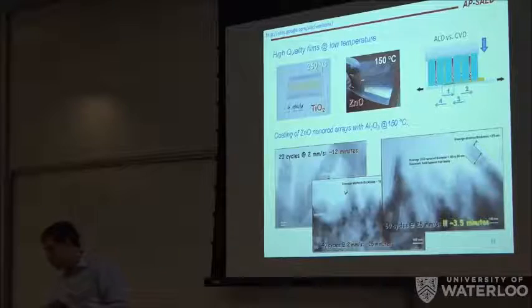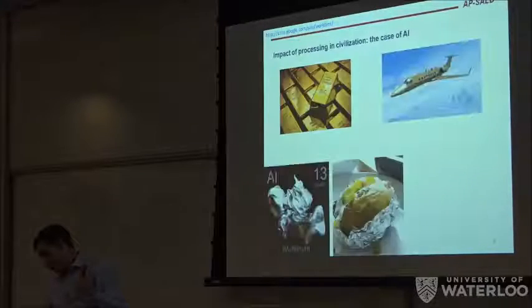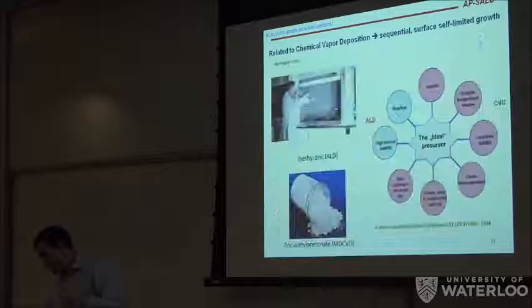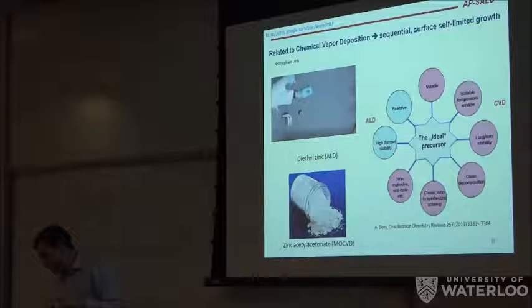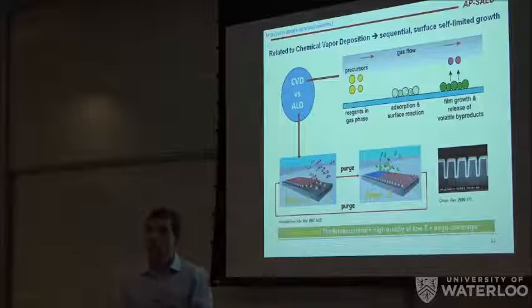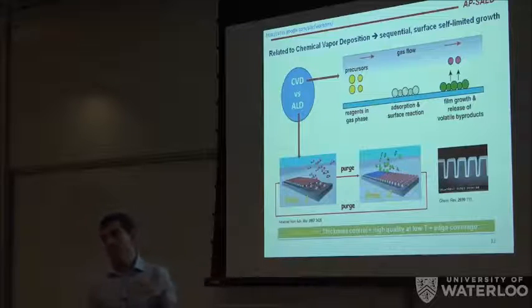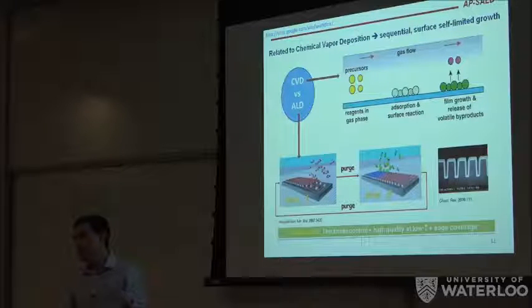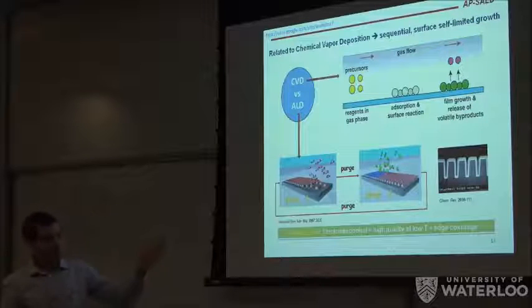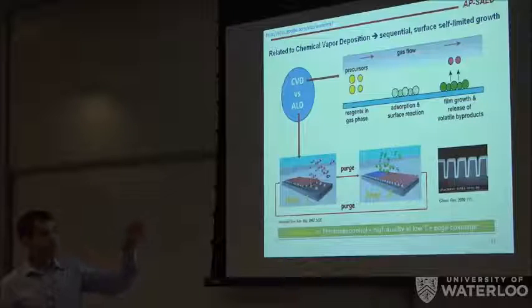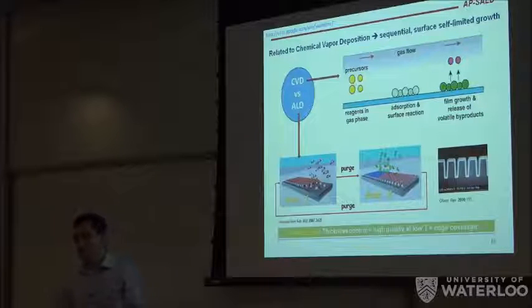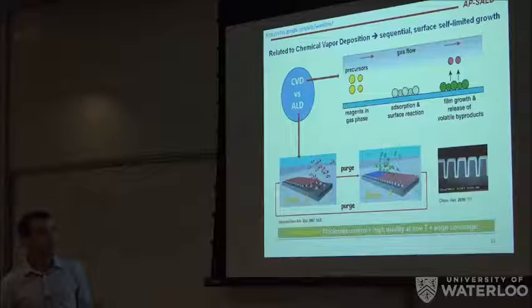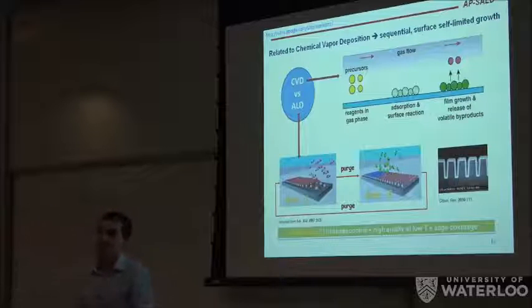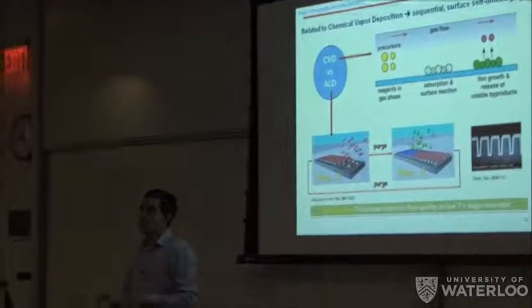On the other hand, if you go to this other case where the trenches are, here you have a really high aspect ratio feature like an alumina template, then you cannot scan as fast. Or you can come up with a head design maximizing the speed at which you can scan. But of course, you need to give enough time for the gas to reach the bottom, and for the inner gas to leave to clean the pore, and so on. So you can still make it. We haven't done it yet in a systematic way, but I'm sure that the speed with the current head as we have it will not be as high as with a flat surface. Yeah, definitely.